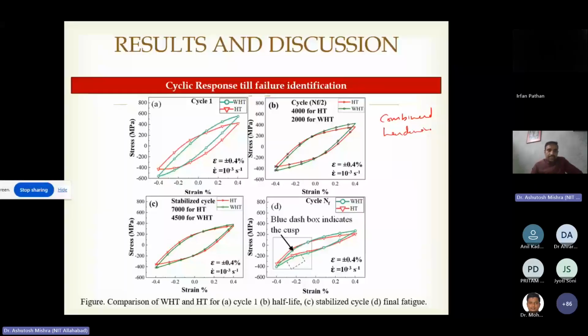Now, if we see cycle 1, half cycle, then we have a stabilized cycle, then failure cycle. So at failure, a cusp has been observed. The cusp in the curve actually tells that the fatigue crack initiation has taken place and we need to take the sample out. So numerically also it is very well predicted, and this is for HT and WHT specimen predicted experimentally. Numerically, if we want to predict this cusp, it is very difficult.